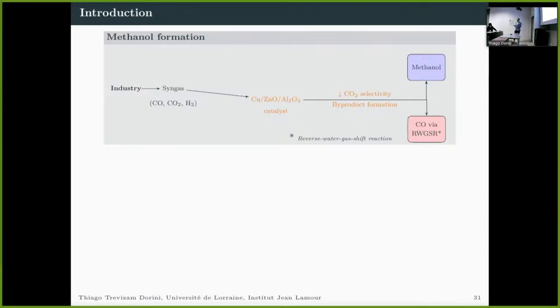Methanol is a very important molecule for the future of energy because you can store it in liquid form, and you can get hydrogen from this molecule by using the reverse water gas shift reaction. Here I highlight one of the processes used to form methanol. In industry, you have many gases that are byproducts of reactions, such as CO, CO2, or even H2, and you use a general copper-based catalyst to form methanol. The problem with this catalyst is that it has very low CO2 selectivity, and many byproducts form, especially CO, due to the reverse water gas shift reaction.